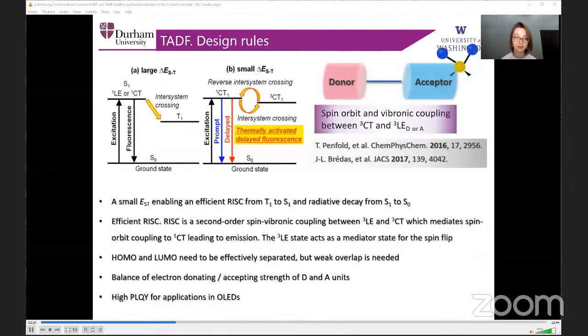Speaking about the molecular design rules for the TADF emitters, they have been polished throughout the years. However, here you can see one of the most common molecular designs, utilizing a rigid donor and a rigid acceptor linked covalently by a nitrogen-carbon bond. We have to ensure a tiny rocking of the donor-acceptor to have the radiative decay. Also, donor and acceptor units have to be balanced, and their HOMO and LUMO have to be separated, though showing a tiny overlap to ensure good optical properties. Also, we are looking for a small delta EST